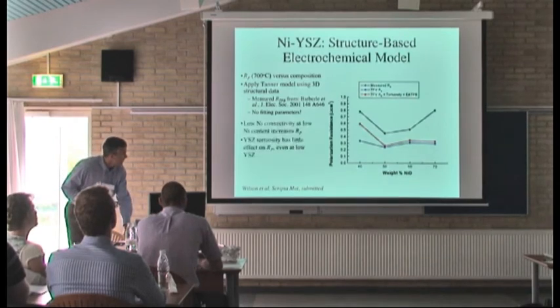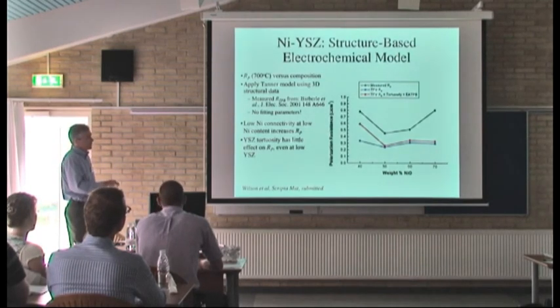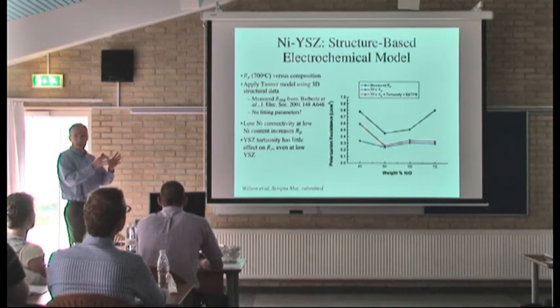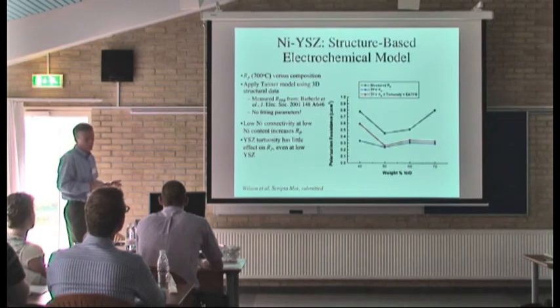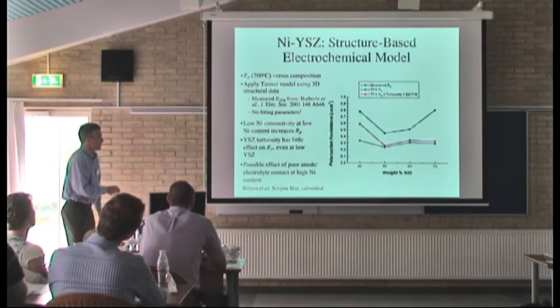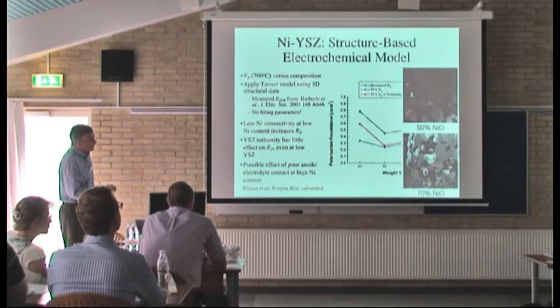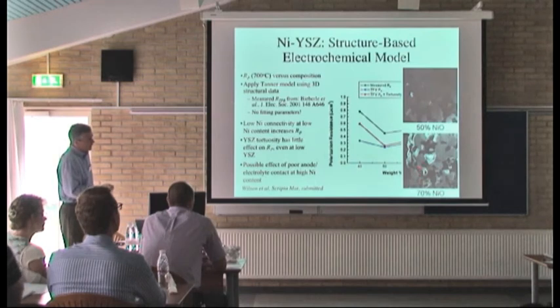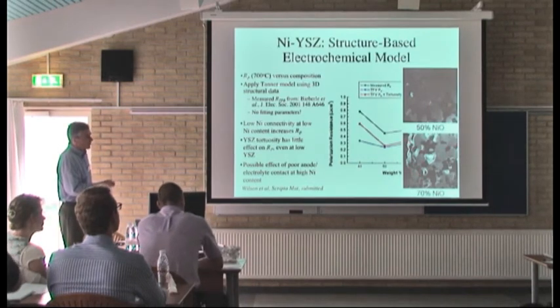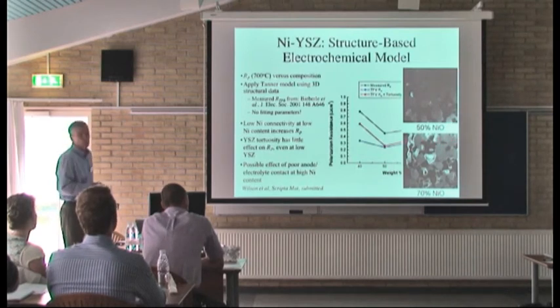This was actually one example where we think interfacial effects may be responsible. We're looking only at the middle of the active layer, not at the interface between the nickel-YSZ and the YSZ electrolyte, so there may be actual effects of those interfaces. Looking at the actual images at very high nickel oxide content, we see a tendency for a lot of porosity and a lot of nickel interfaces. So there's a real question whether there's a much higher tortuosity in the YSZ phase at that interface, making it very difficult for oxygen ions to transport into the electrode.